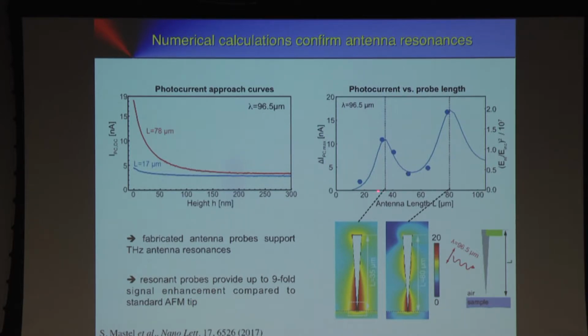So here we measure the photocurrent. We place this tip above the photodetector, and we measure the photocurrent as a function of tip length, and then we see these oscillations. We see that the photocurrent goes up dramatically if we go to very long tips. We performed the numerical simulation here, and we could identify these peaks. These are the fundamental antenna resonance, and this is the second order resonance. And so I think this is another thing to do, engineering these tips and making them better. That's another possibility to get out more photons in an experiment.